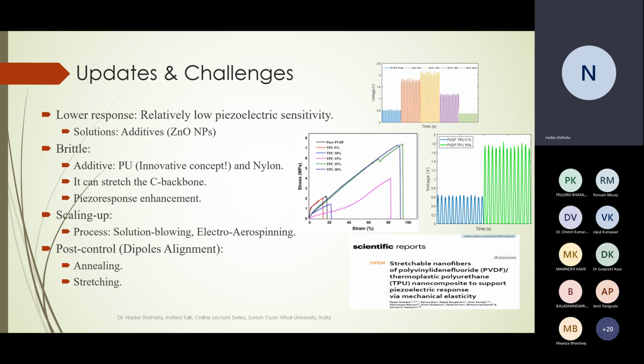And this is an innovative concept that some research groups worldwide have been working on over the last 2 years. Here, the idea is to depend on the better stretching of the carbon chain backbone inside the monomer chains, so that it acts as a stretching of this backbone, and consequently you are increasing the distance between the positive and negative charges, increasing the dipole moments, and consequently you will have a better piezo response.